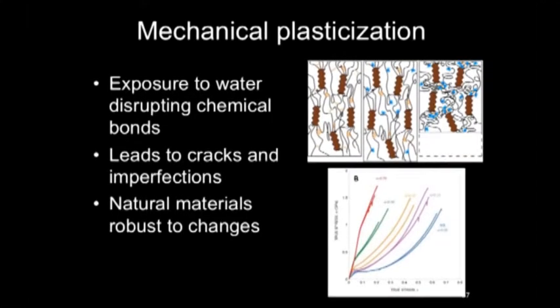of silk? But the problem is measuring this and decoupling it from the effects of water at the adhesive interface is quite difficult, mostly because, as you've seen before, these are either performed underwater or these materials have some kind of gluey, water-based adhesive that keeps the fiber hydrated. So we had to find a model that wasn't initially wetted, and cribellate silk is the perfect model for this.